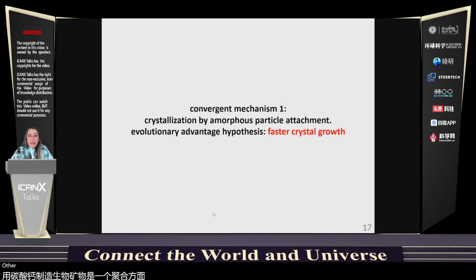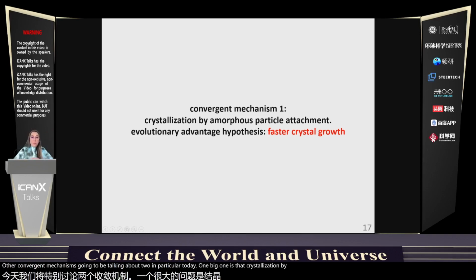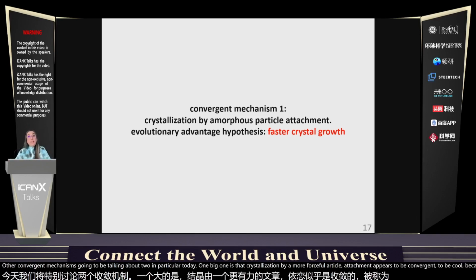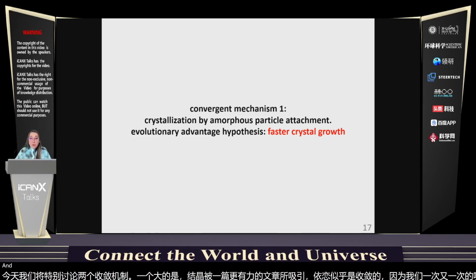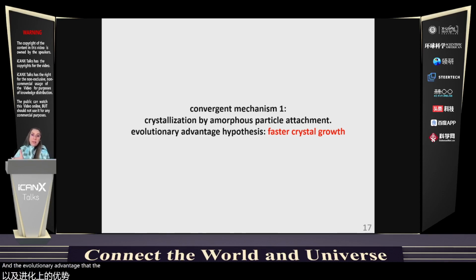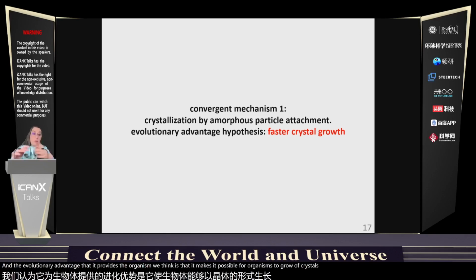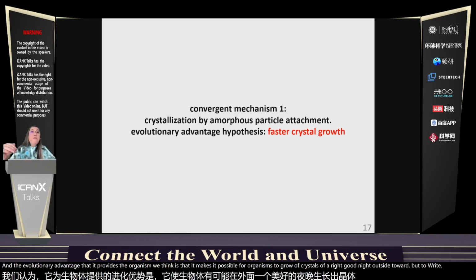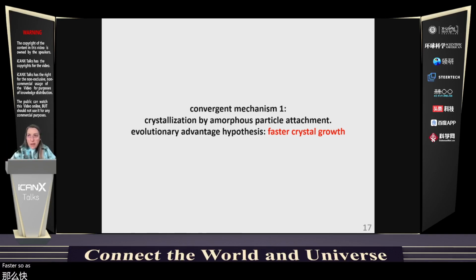Other convergent mechanisms, I'm going to be talking about two in particular today. One big one is that crystallization by amorphous particle attachment appears to be convergent because we observe it again and again. And the evolutionary advantage that it provides the organism, we think, is that it makes it possible for organisms to grow crystals of aragonite, calcite, or vaterite faster. So achieving faster crystal growth is possible with amorphous precursors.